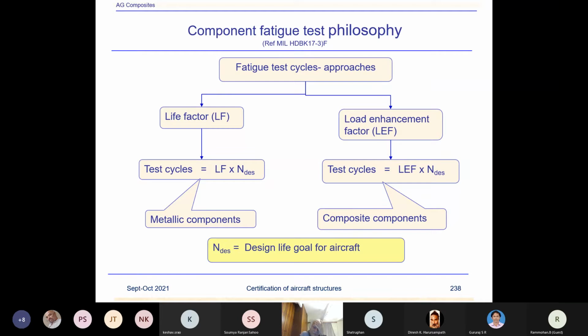If it's a composite structure, that strategy doesn't work. The problem with the composite structures is that it has a very large scatter factor compared to a metallic structure. So due to the scatter factor being large, and usually the factor comes out to be around 10, 12, depending upon the mode of failure, and if the scatter factor demands the life factor to be around 10 or 12, it becomes impractical to test a component.